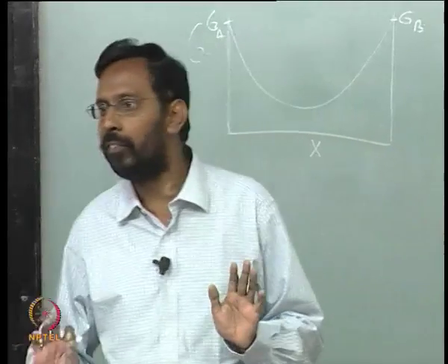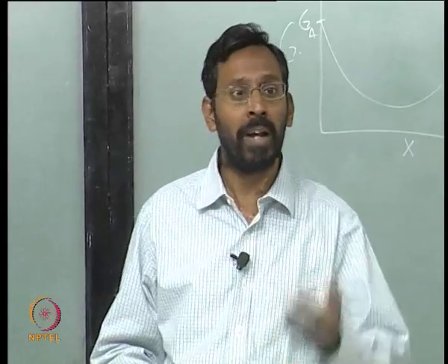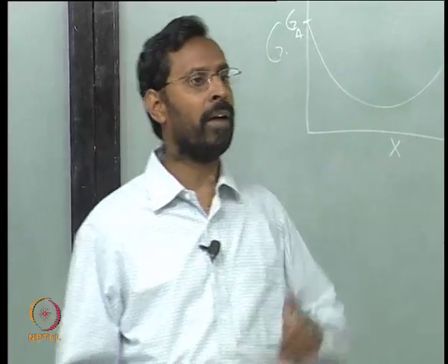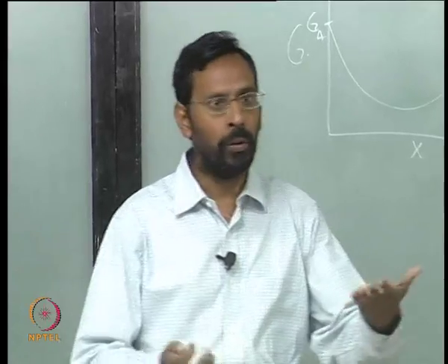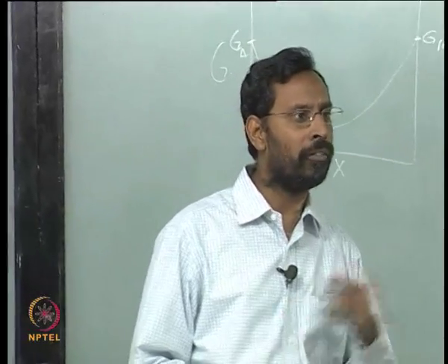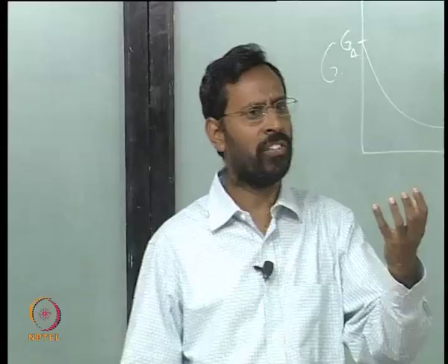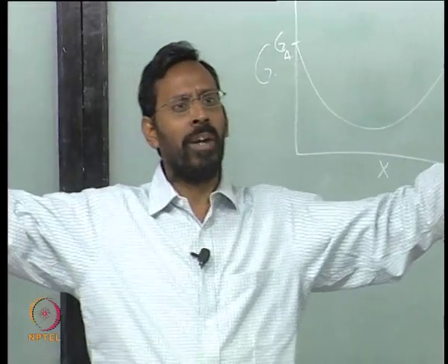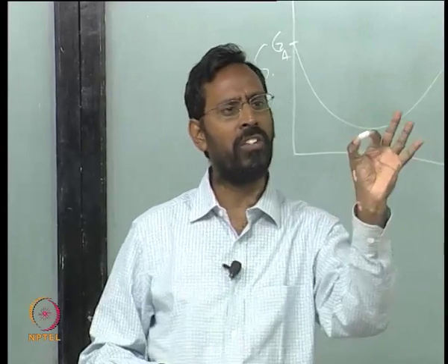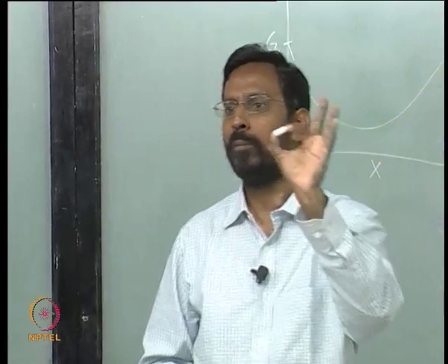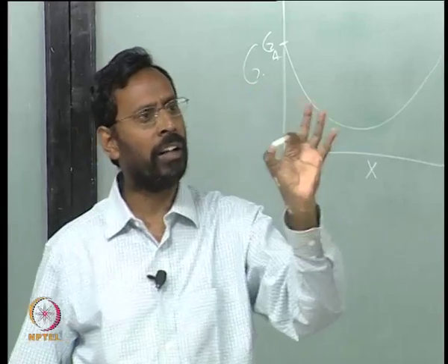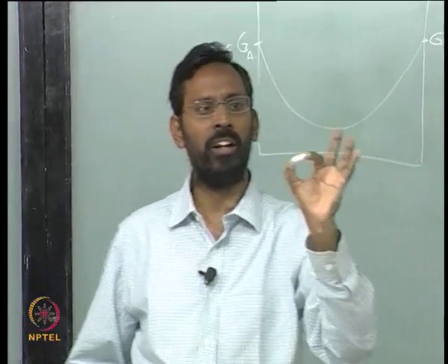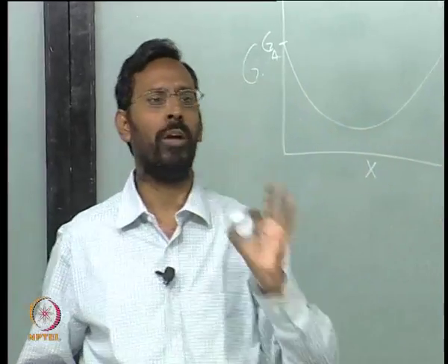I cannot calculate the free energy of anything else from the Cp, because Cp is that of diamond cubic silicon. What I am doing in calorimetry is finding the heat capacity for a stable state. I cannot find the heat capacity for something which is metastable, which does not exist. If I put this sample into a calorimeter and measure the Cp, I would get the Cp of that particular structure, which is stable at those temperatures.